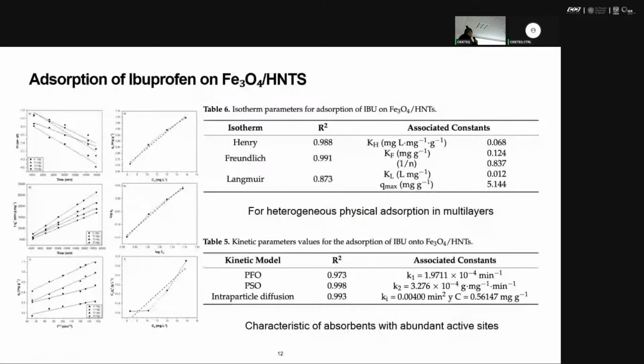So as I found, as I said, it's a low concentration, a low adsorption, and it's physical heterogeneous adsorption. So it suggests that the adsorption is going through hydrogen bonds. That is the reason why it's very weak and why it's not very useful. But well, this kind of experiment could describe that process.